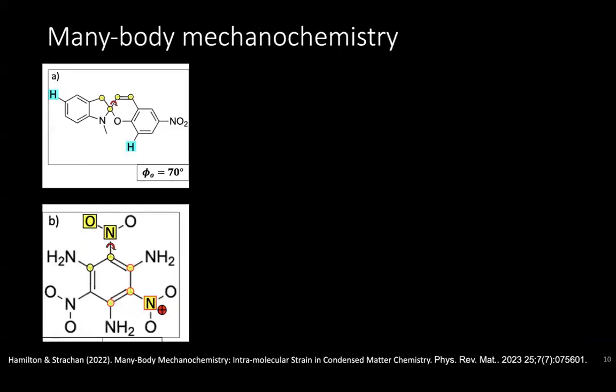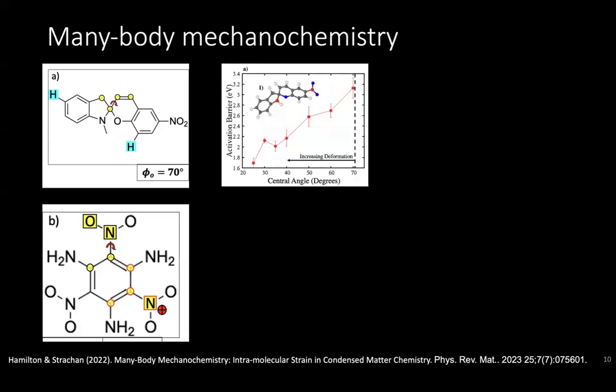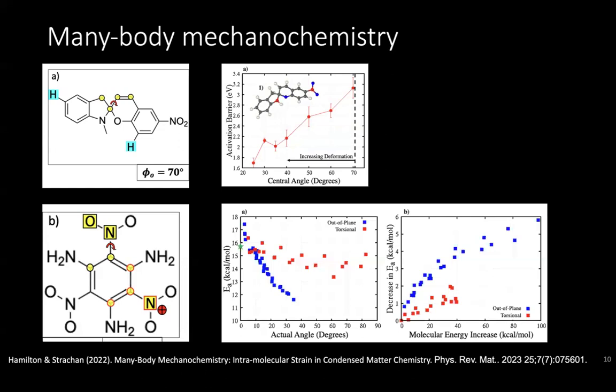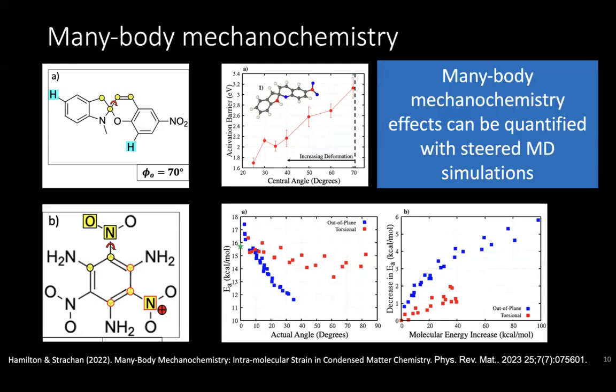So we developed a simulation technique where we can go into the energetic material, this is the mechanophore, this is the energetic material, and apply external many-body forces and distort the molecule, and then look at the effect on chemical kinetics and decomposition time, okay? And we showed that adding this external potential, instead of pulling, elongation, distorting, has an effect on the activation energy. It has an effect on the chemical kinetics that matches what we see in these gigantic dynamical simulations around the hotspot, okay? And again, we call that many-body mechanochemistry. I think this is an effect in polymers. It's very important. If you imagine condensed phases, you really almost never have elongation, but your molecules are going to be distorted, strained in many-body manners.